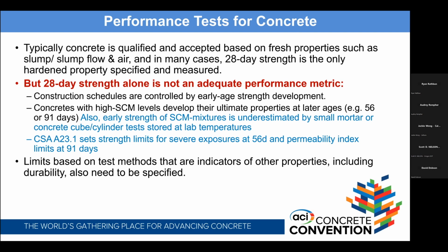And also when people talk about low early strengthening of high SCM mixtures, if you only cast cylinders, like a 6x12 cylinder or 4x8 cylinder, and store it at a constant temperature in a lab, you're underestimating the development of properties in that concrete, because concretes containing SCMs are far more thermally sensitive. With the heat of hydration builds up, the temperature rises, they accelerate a lot faster than a Portland cement mix. So if you keep them at a standard 73 Fahrenheit in a curing room, you're not seeing that potential development. So the in-place development of strength is often much higher than is predicted by cylinder tests.